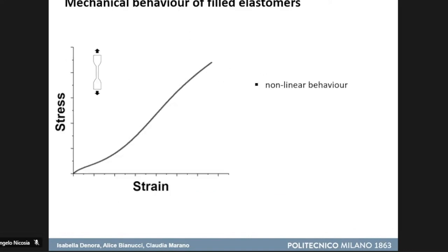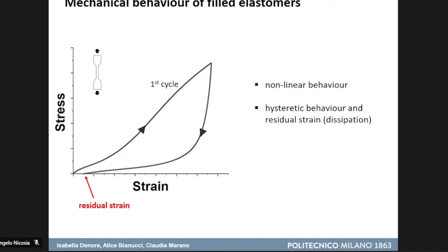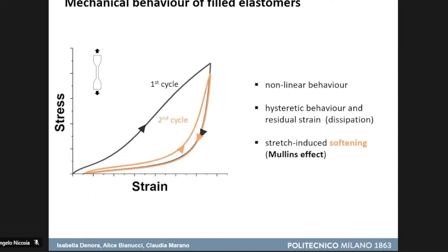If we perform a uniaxial tensile test on a dumbbell specimen, we obtain this type of curve, so we can observe a nonlinear behavior of this type of materials. If we then unload the specimen, we can observe lower stresses, and this is due to a dissipative behavior of the materials. At the end of the cycle, we can also observe a residual strain. If we load the material again, we can observe that the stresses exhibited in the second loading are lower than those experienced during the first loading. And this effect is called the Mullins effect. This is a softening induced by the first applied deformation.